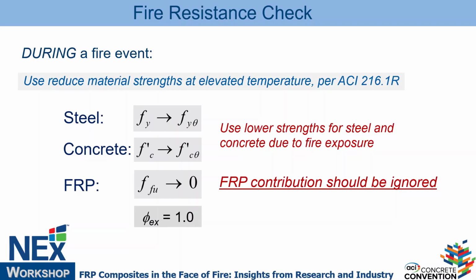Okay, how do we deal with FRP? If I have FRP reinforcement, I said that the strength of the steel will drop, right? So I need to use reduced strength of steel and reduced strength of concrete. Let's say I'm doing shear assessment, not just flexure. FRP, we ignore its contribution to strength, right? That's very clear currently in ACI 440 and also in ACI 562, the repair code. You ignore the contribution of the FRP.